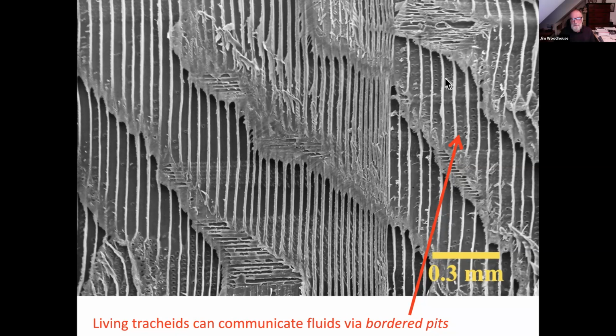They have an important role. When the tree's alive, they do act as valves so they can let the flow through or stop it. In dried wood, these things all close up, and that's why spruce floats when it's dry. It's not easy to get liquids inside it. It will continue to float for quite a long time because there are pores linking the cells, but they're closed.